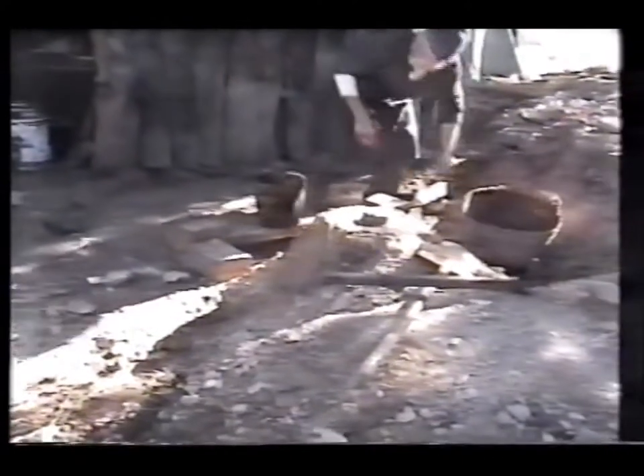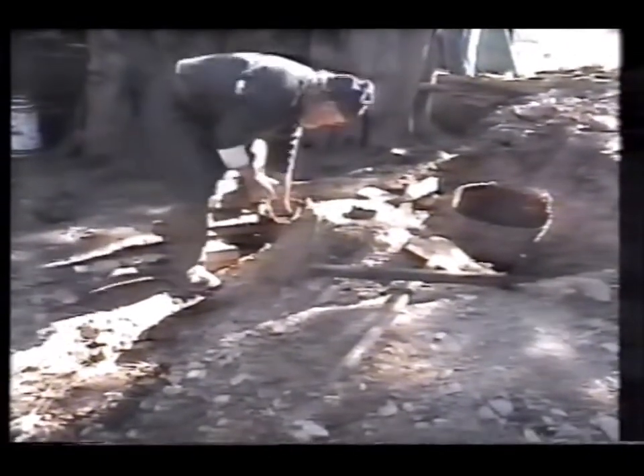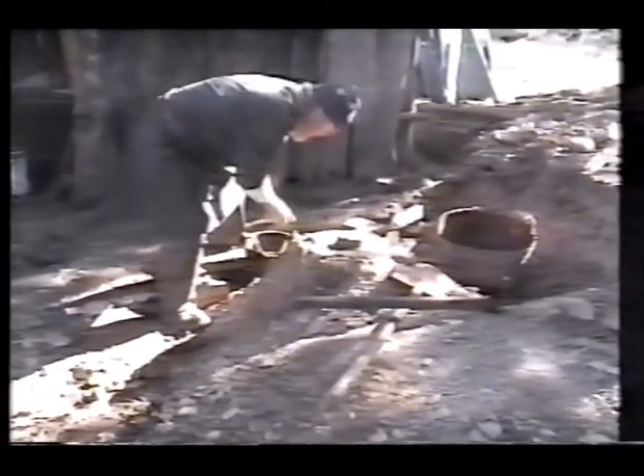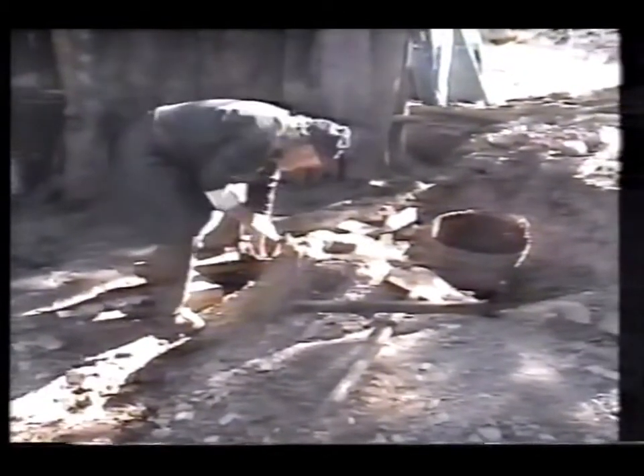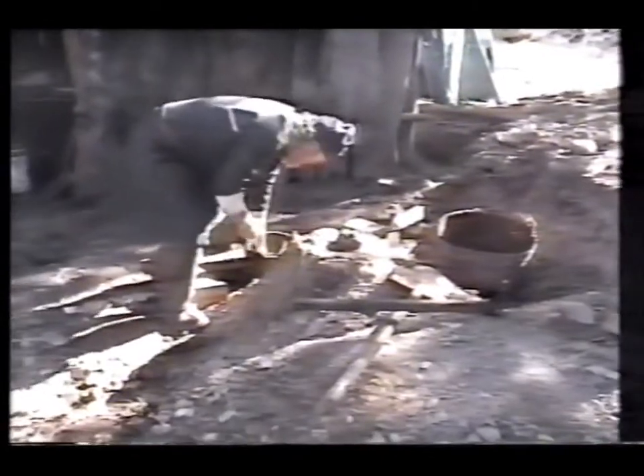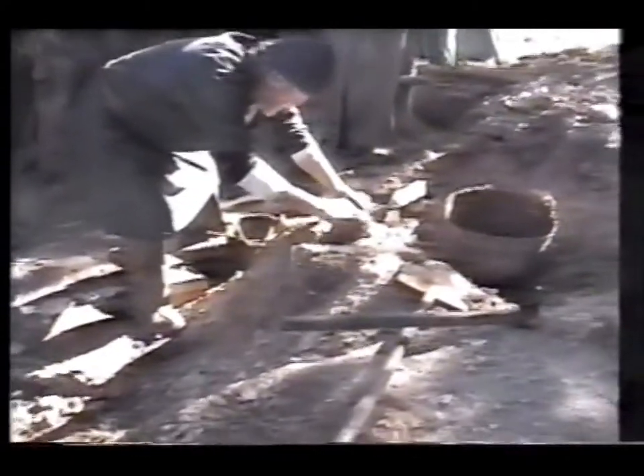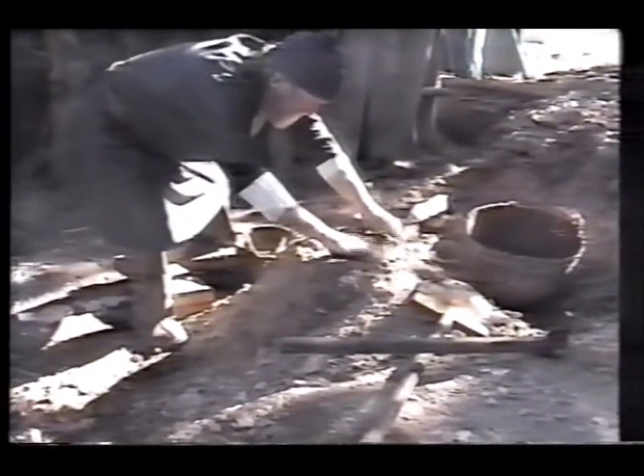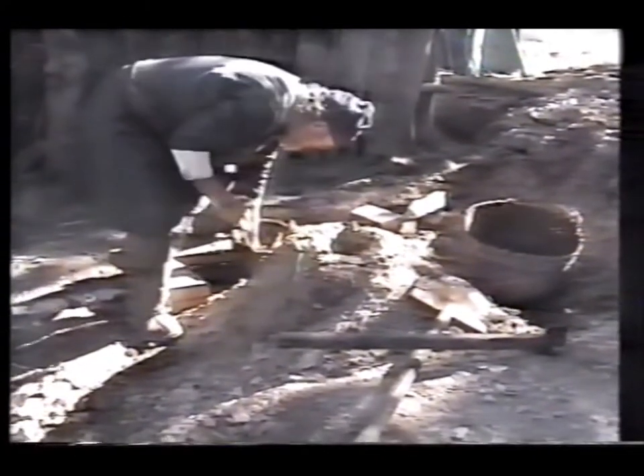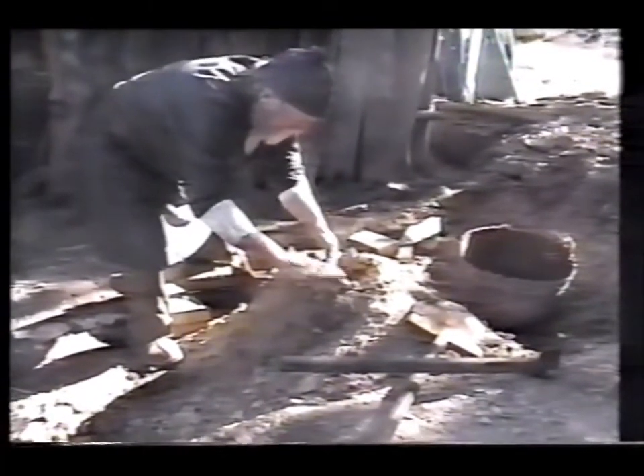Next came the puddling process, where the clay was mixed with water until it reached the required consistency. The clay then would be transported to the site where the bowl hearth would be constructed. Usually this would be a shallow bowl, not quite 30 centimetres across, 9 or 10 inches in the old scale, with a clay cone or dome on top of it, a fire clay lining, and a fire clay tuyere or air pipe coming in from where the bellows would be fitted. And quite often a slag hole would be left in one side, which would be temporarily blocked, of course, and only opened towards the end of the smelt.